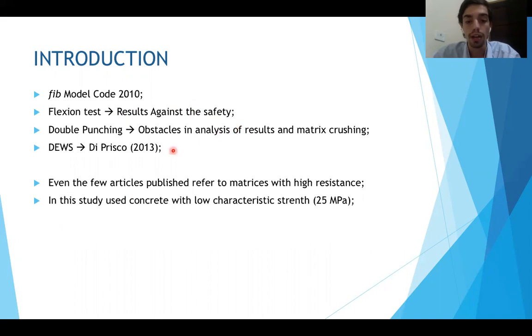To characterize the FRC, we have the flexion test, which offers results against safety, because the fibers act in tensile strength and there is no pure tension, only flexion; there is a portion of compression adding to the resistance. In addition, the specimens are large prisms, which are difficult to handle, especially after being submitted to high temperatures, which makes the concrete matrix fragile. There is also the double punching test, but it causes crushing of the matrix and its analysis is difficult, since the crack, which is a difficult area to be measured, is complex.